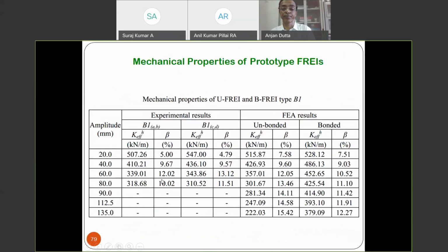Of course, experimentally we cannot really go beyond a certain level because of the safety of the setup. But this 80 millimeter which we have tested is large enough to introduce large nonlinearity into the system, and that is what we have compared with the numerical simulation. They have a very good match, and with this we have gone further in numerical simulation.